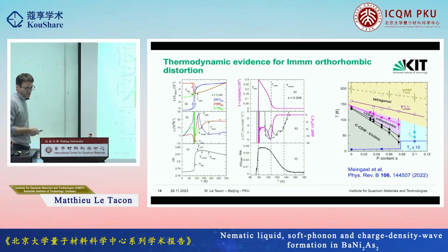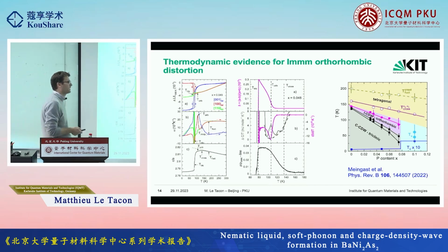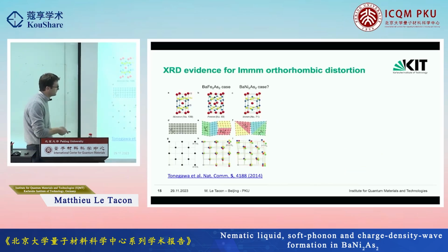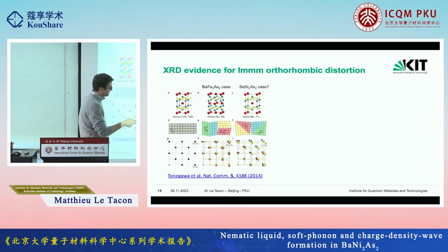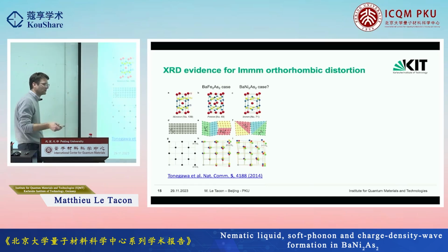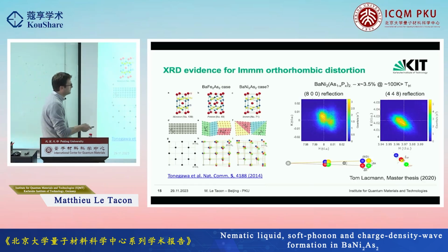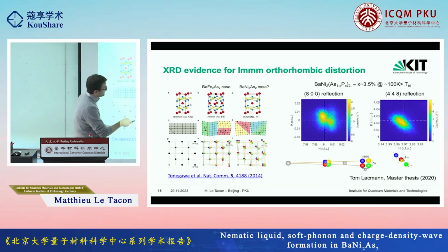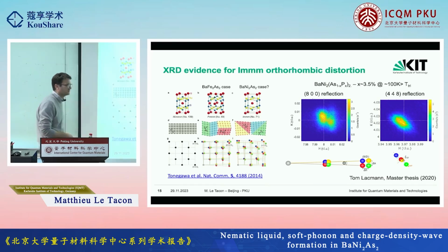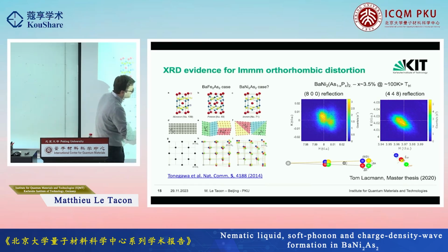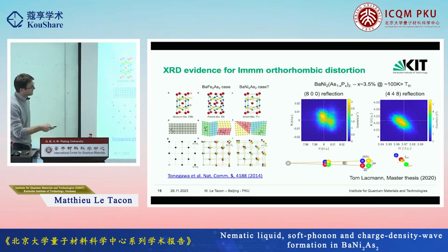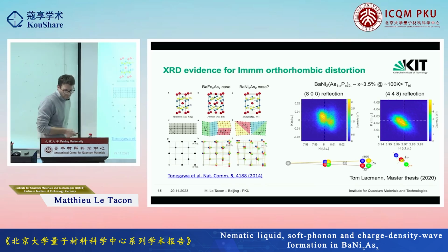One question that also came up is, can we see that with X-rays? It turns out it's very hard with X-rays, and you really have to use the highest resolution setup. In that case, we used our four-circle diffractometer. We closed all the slits and went for a large reflection, and indeed, instead of seeing this nice point reflection, you can see that there is some kind of spread corresponding to the domain formation in this compound. For the 800, it looks more like this, and for the 448, it is this spread, as you would expect for this kind of distortion. Again, this is something you can only see in the doped compound, where the distortion is established.